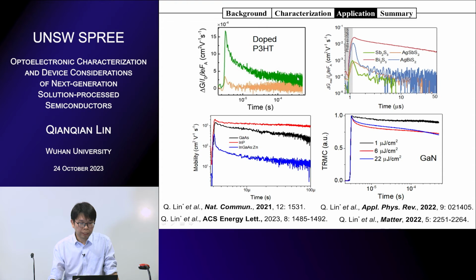We can measure a lot of materials based on the TRMC method. Recently we measured typical organic materials like P3HT. We can also measure chalcogenides. Mainly we are working on bismuth sulfides, antimony sulfides, or silver bismuth sulfides. It works well. We can also use these methods for commercial semiconductors like gallium arsenide and indium phosphide, and it works much better than solution-processed materials because the signal or the mobility is a few orders of magnitude higher.